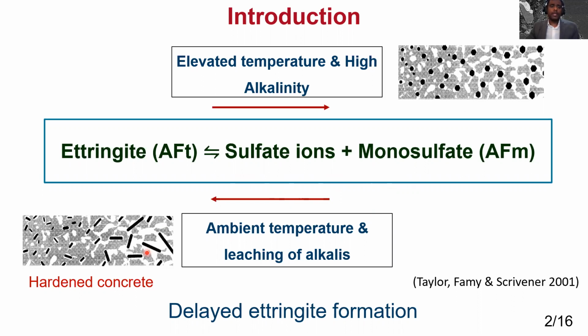The quantity of ettringite precipitating in the confined space may be the deciding factor whether the system will be expansive or not. However, to understand that, we have to wait for months, if not years, to know whether a system is expansive or not. So, if we can understand this in a few months of time, it will be very, very beneficial. So to understand this, we think studying the early age pore solution chemistry of cementitious systems will be helpful.